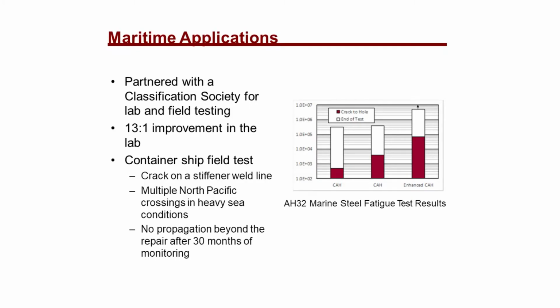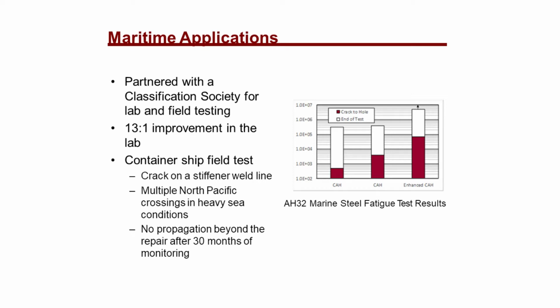Then with our maritime application, we partnered with a classification society. We did another test in the lab, showing a 13-to-1 improvement using their steel material, AH32, which is a little different from A36, which is what you normally have in your bridges. Then we did a field test on a ship going back and forth across the North Pacific. This ship went from the San Pedro, Long Beach area up the Pacific coast, even made a stop in Tacoma, and then crossed the North Pacific to go to Korea. We monitored this for 3 years, going back and forth.